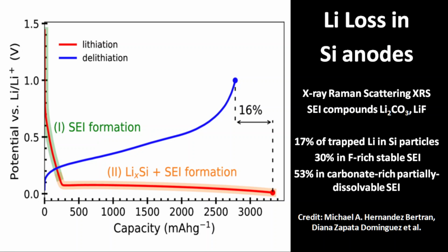30% of the carbonates formed during the lithiation are dissolved on delithiation. 17% of the lithium loss in the first cycle is trapped in disconnected silicon particles, while 30% form a fluorine-rich stable SEI. 53% of the lithium is in a carbonate-rich, partially dissolvable interface layer.